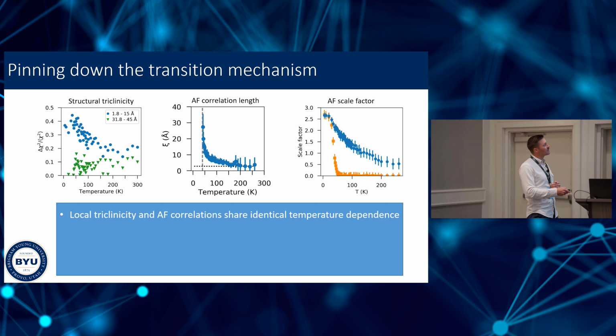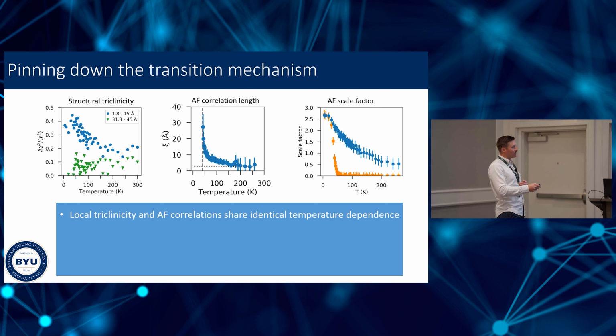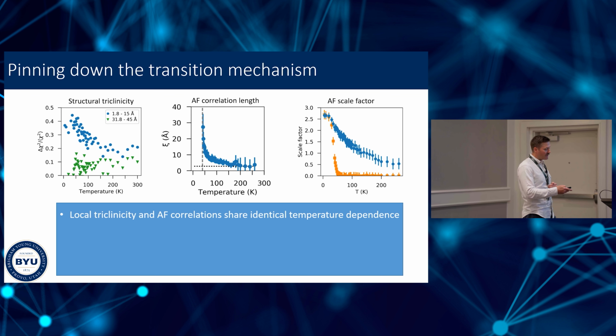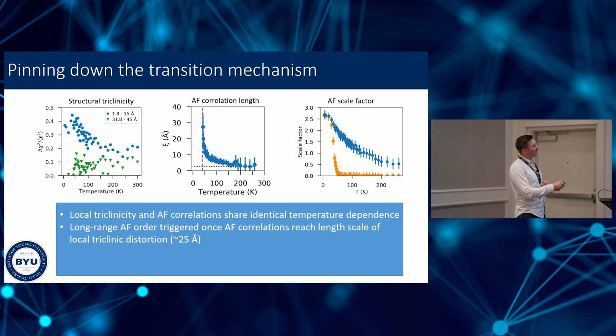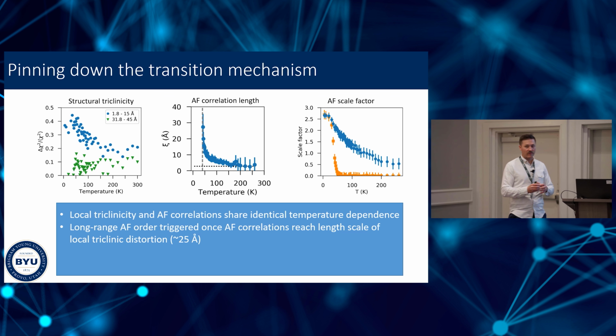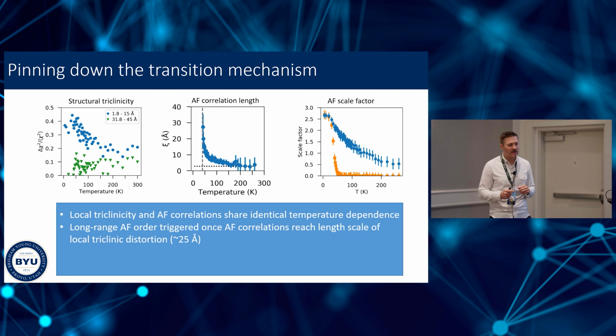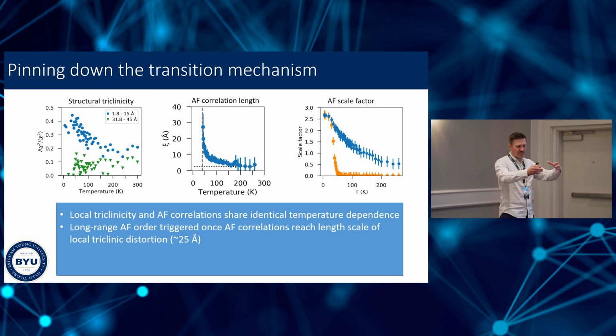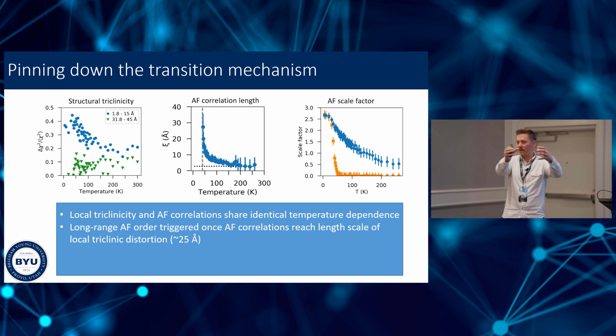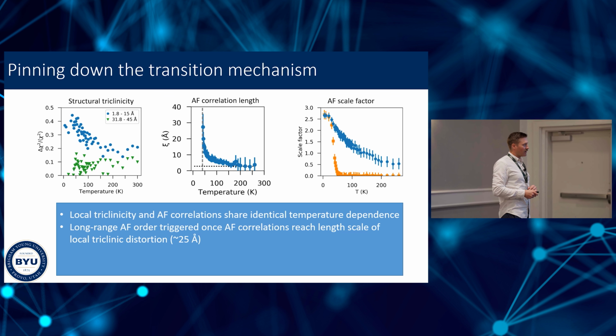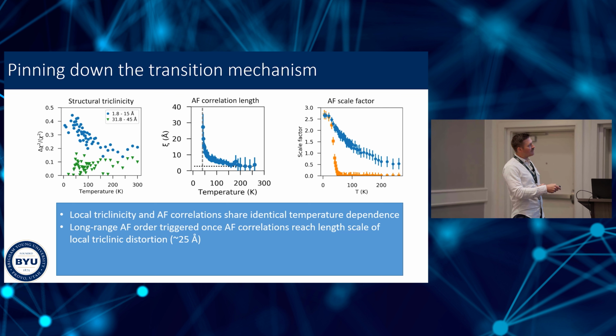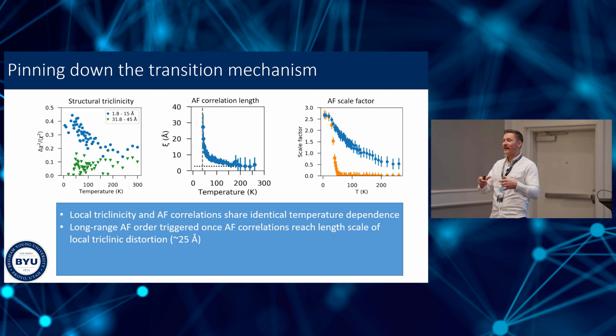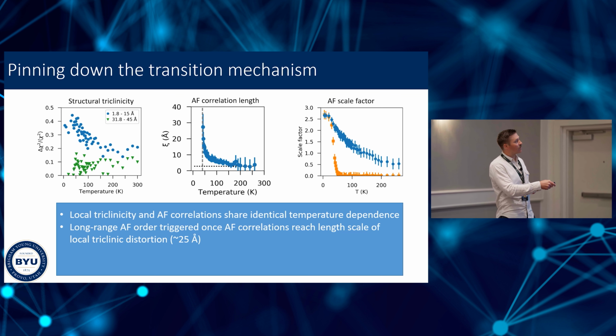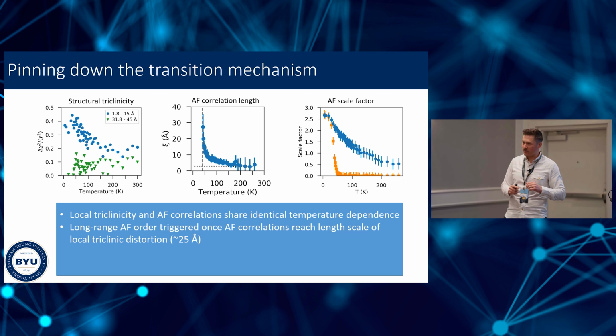So this suggests some interplay between this local triclinic distortion and the growth of these antiferromagnetic correlations. If we remember that the length scale of the local triclinic distortion was 25 angstroms, and that was relatively independent of temperature, we have these 25 angstrom puddles of local triclinic distortion in our structure. Well, as soon as the antiferromagnetic correlations reach that length scale, 25 angstroms, that's when the long-range order is triggered, okay? 25 angstroms right here, boom, we move into the long-range ordered magnetic state.